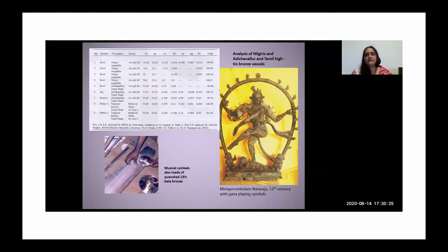Another interesting aspect is that the martensitic beta phase is also responsible for giving certain resonant properties to the bronze. When you strike it, it gives off these very high-pitched tonalities. And quite often, the cymbals, now this has also changed, many have stopped making high-tin bronze cymbals and are making other kinds of cymbals of brass and so on. But traditionally, there was a tradition of making musical cymbals from this quenched beta bronze.